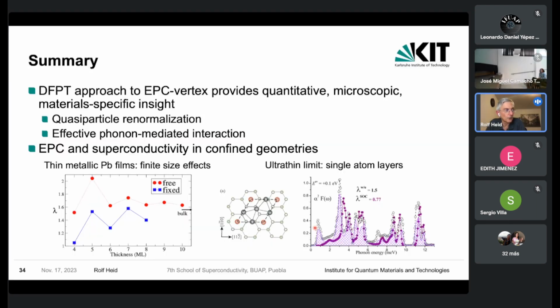And that allows to look in very much detail onto the quasi-particle renormalizations of systems and the effective phonon-mediated interaction. And I've shown you some examples of such studies where we looked at the electron-phonon coupling and superconductivity in confined geometries. We have shown that also these kind of quantum size effects can be somehow transferred to superconducting properties due to the confinement of the vertical motion in thin metallic films.